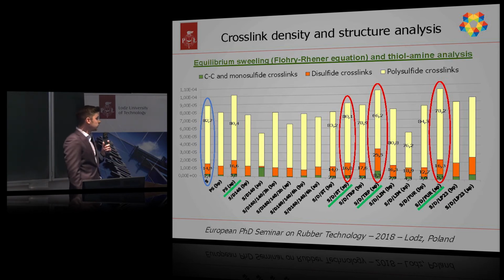So when it comes to the crosslink density and structural analysis, I carried out equilibrium swelling of vulcanizate, and then I calculated the crosslink density from the Flory-Rehner equation. I also performed thiol-amine analysis to indicate how many polysulfide, disulfide, monosulfide, and carbon-carbon crosslinks participate in the rubber structure.